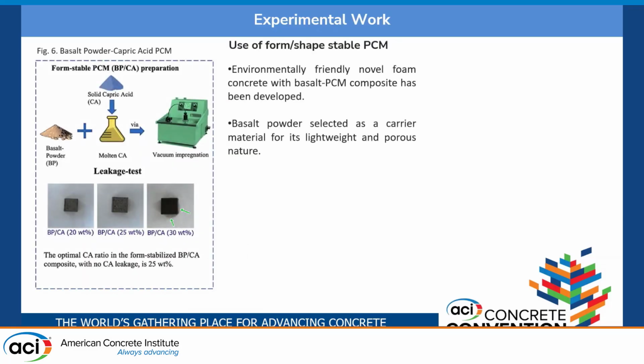Besides that, we have used some form-stable PCMs in which we have used basalt. We have produced foam concrete through this. We have used basalt powder, which is environmentally friendly, a waste-based material coming from the basalt quarries. And we have used solid capric acid as a PCM. We have melted this, and we impregnated using the vacuum impregnation technique. We have incorporated these materials into our porous basalt powder. We do some leakage tests to optimize the PCM ratio in our composite PCM.